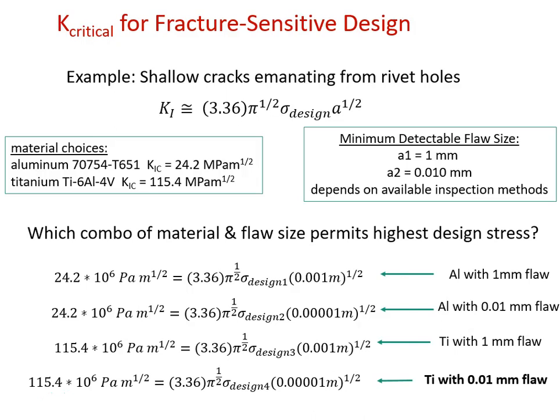So we can be sure in the second case that we don't have any flaws bigger than 0.01 millimeters. Well, if we plug those two A's into our K1 expression, we can solve for a design stress that would make sure that the K applied did or didn't get above the K1 critical for the material. So if we look at our first calculation, combining material and flaw size, let's look at what it would take in terms of design stress to exceed K critical for aluminum, which is 24.2 megapascals meters to the 1/2. We would have our K applied expression with our Y, 3.36, pi to the 1/2, multiplied by our design stress. And with the larger minimum detectable flaw size, we'd put in 1 millimeter for our A, which is 0.001 meters. So that would be aluminum with a 1 millimeter flaw.